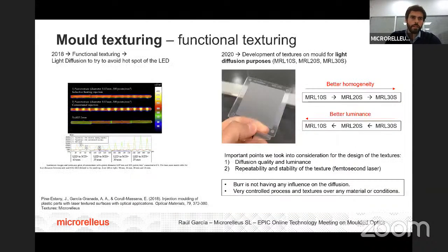Regarding functional texturing and light diffusion, 3 years ago we did a project trying to avoid the hotspot of the LED, texturing the mold and injecting transparent PMMA. We had some problems in terms of repeatability and so on, because we used a nanosecond laser.